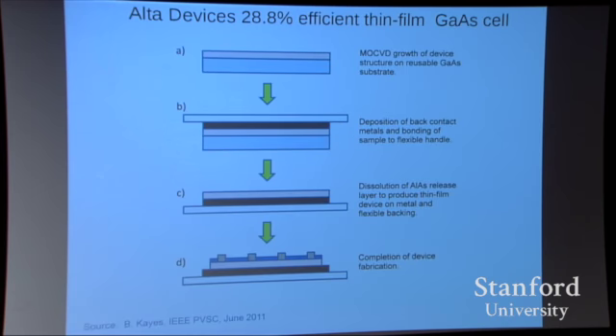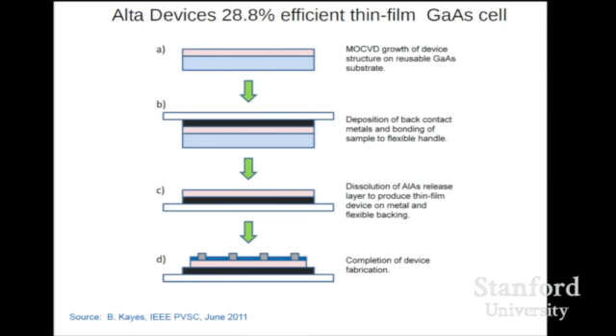So Alta Devices has really changed the game with the wafer cost itself. And the idea here is that you grow your gallium arsenide on top of just a little bit of aluminum arsenide. And you can etch aluminum arsenide without etching gallium arsenide. And that means that you can take your solar cell off of the wafer. Now you have a very thin solar cell, and then you can polish the wafer and reuse it and potentially use it as many as 1,000 times. And so that greatly cuts down on the costs associated with having these single crystal substrates. However, you still have to grow the III-V semiconductor, and that itself can be expensive.